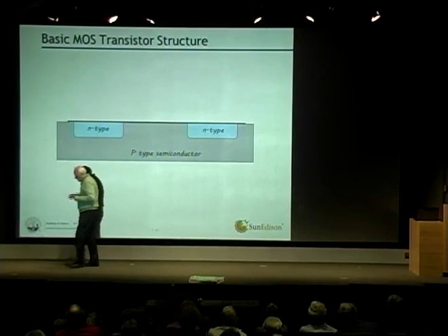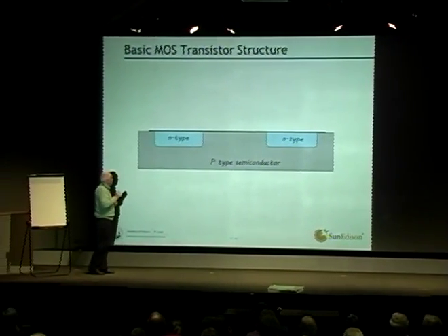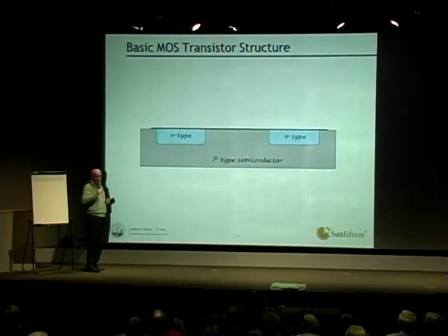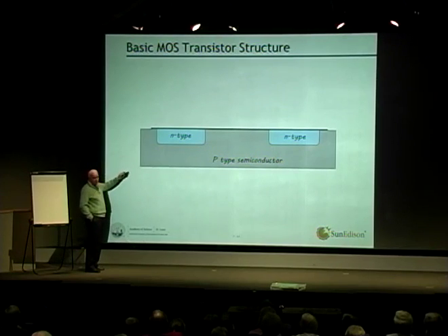They do this by taking the phosphorus atoms and putting them in a machine called an ion implanter. They ionize a gas with phosphorus in it, and accelerate the phosphorus to very high speed, and it hits the silicon so fast that it embeds itself in the surface just a few microns in. Actually a fraction of a micron, and they heat it to diffuse it in a little bit further.